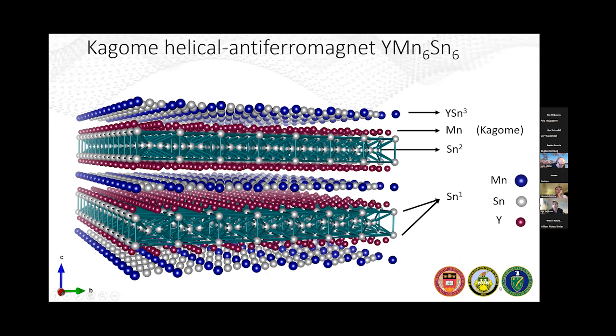this is the layer structure of this system. So it consists of tin slabs that basically have a manganese kagome layer on either side, and this tin manganese structure is sandwiched between these yttrium tin layers that are the gray and blue here. It looks like these crystals are actually nice and layered. They're actually quite difficult to cleave.